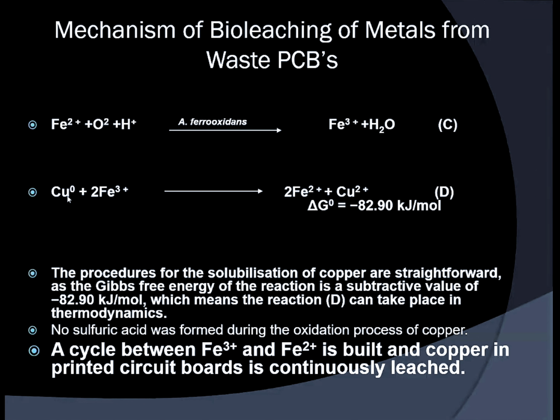We are calling it a zero oxidation state. So the ferric ion is oxidizing this copper, thereby the copper will be converted into Cu2+. Cu2+ is the form of copper in copper sulfate even, right? So Cu0 is converted into Cu2+. Fine. And now the ferric itself is converted into ferrous. It means ferrous, which is a food for the bacterium, is regenerated. This is the beauty of the technology. The food for the organism is regenerated, thereby reducing the cost of the process to a greater extent.